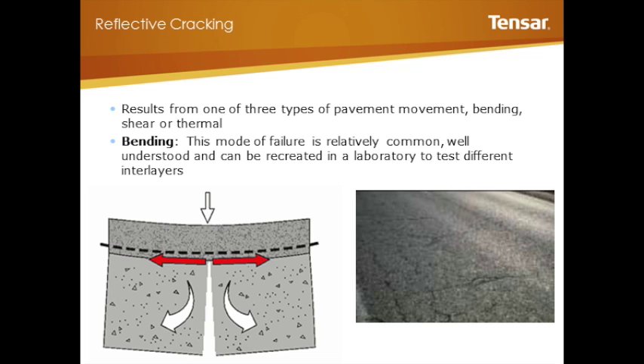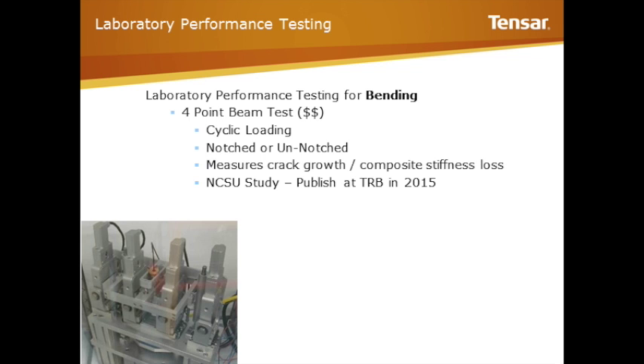Okay, so the first type of reflective cracking that would be of interest to you, and it relates to that first poll, the second poll question, is the one of bending. So that's typically where you have a crack sitting in a pavement, you stick an overlay on it, and nothing happens until a vehicle drives over it. Then your pavement structure flexes, and that deflection is basically associated with moving the crack. So that crack, that strain then develops at that point and wants to reflect up through your overlay. This type of crack is a match made in heaven with your interlayers. It's an easy one for the interlayer to address, and typically the boundary conditions are not as rigorous as they are for other distress types. So that's a good thing.